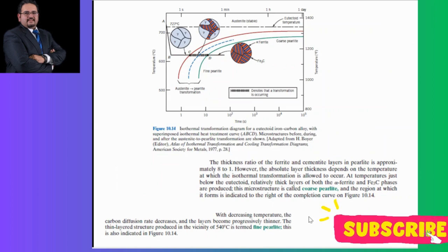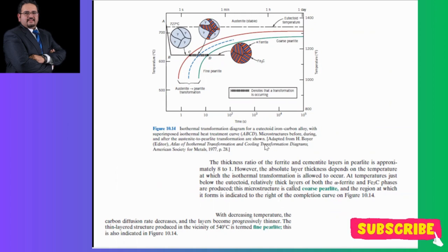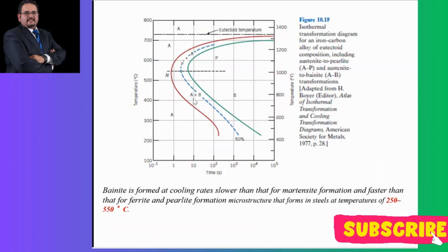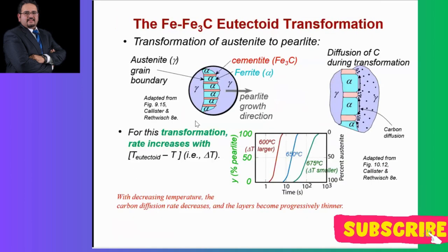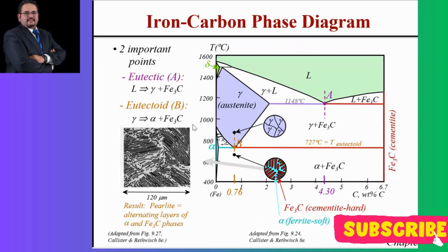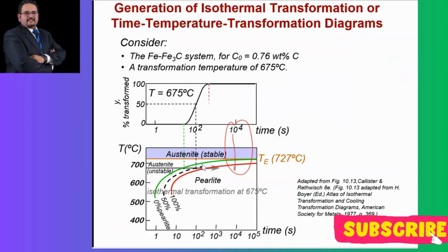Any concern, students? But sir, why is martensite not there in the phase diagram? Why is martensite not present in the phase diagram? No, in the phase diagram, you don't have time. If you see the phase diagram, you do not have any place for time. You just study the temperature and the composition, right? So in the phase diagram, this is one reaction. You don't know the possibilities. In order to understand the possibilities, you need to use this diagram in combination, the one that is here.